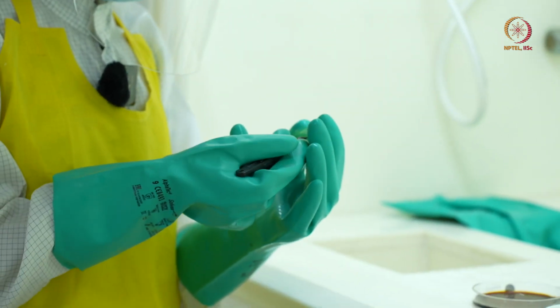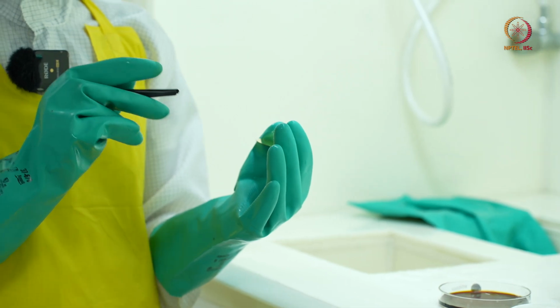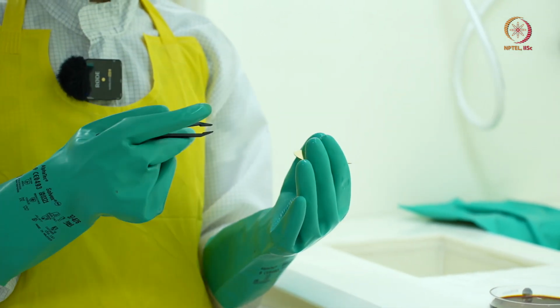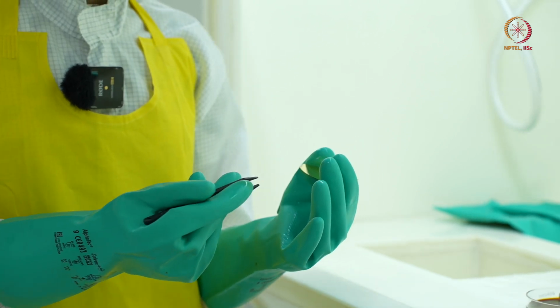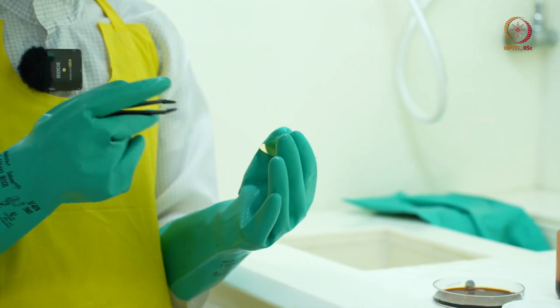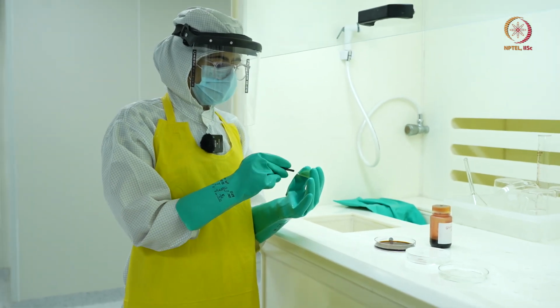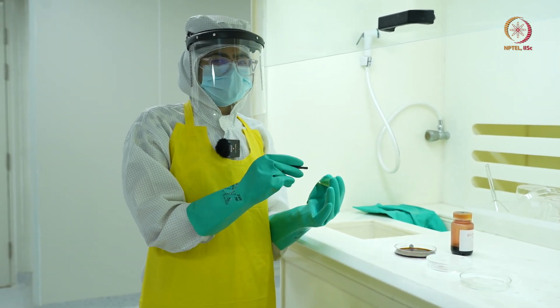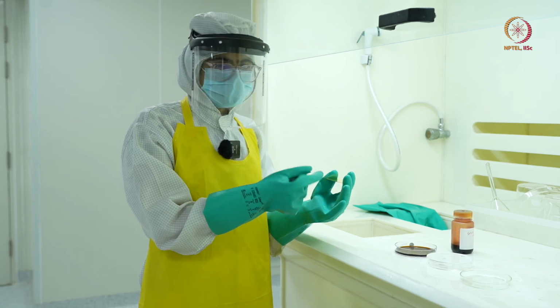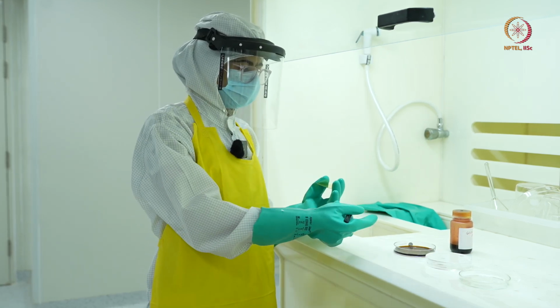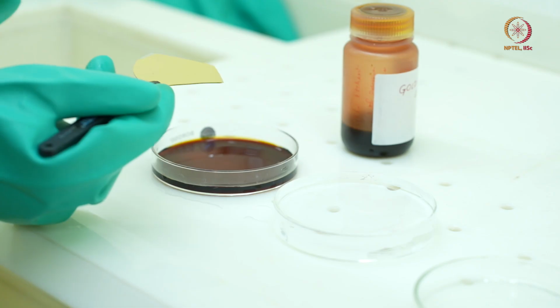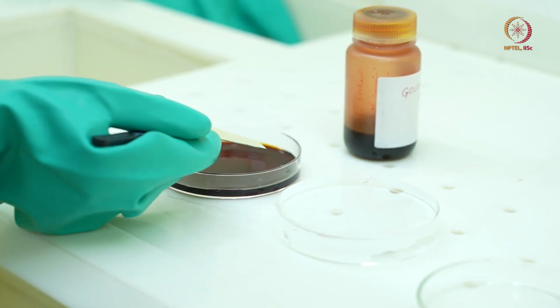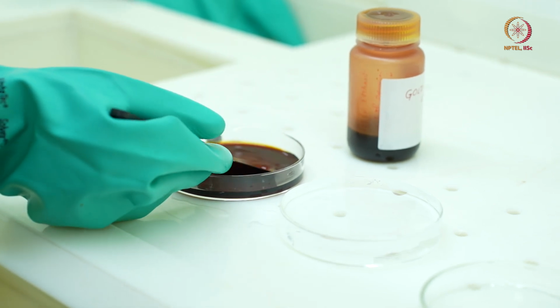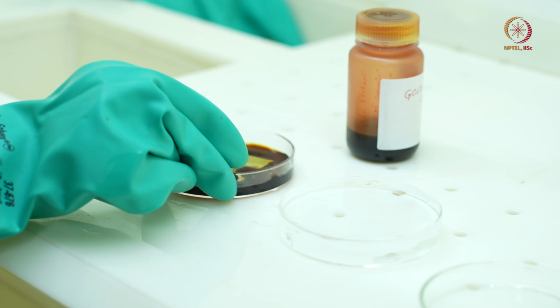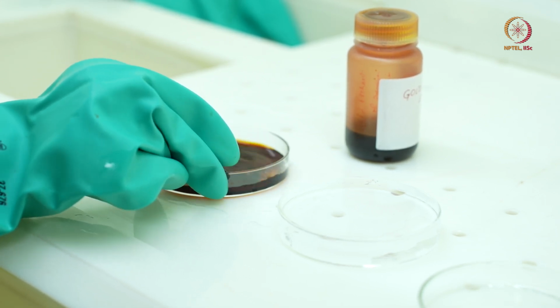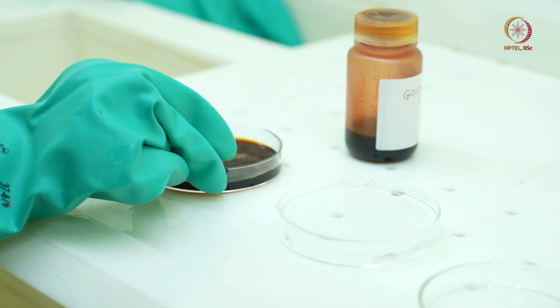So before putting it in, this is a timed etch. However much my thickness is, it will etch for that much amount of time. The ideal etching rate is 0.5 micron per minute. So I have 200 nanometers of film, so it will take about 30 seconds to etch, and that I can visually see when my sample is inside the gold etchant. So I am putting the gold sample inside the gold etchant, and I'll start agitating it so that the etchant comes over the sample, and I'll agitate for 30 seconds.